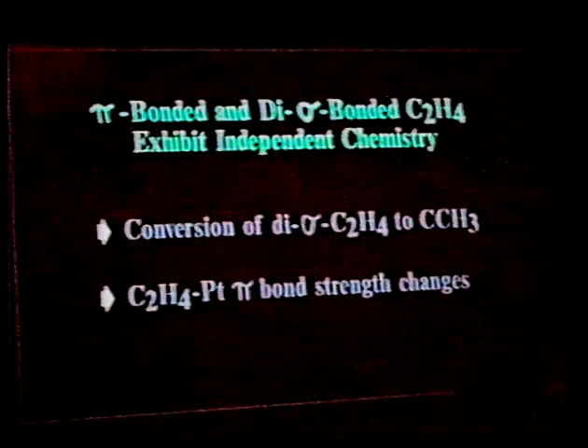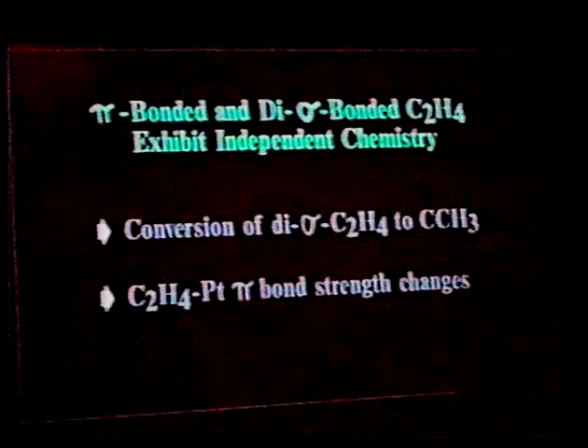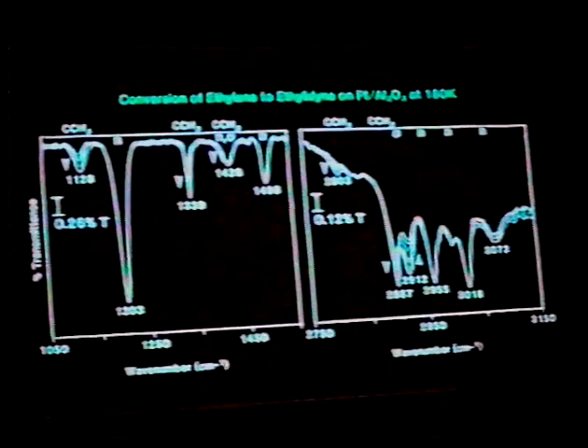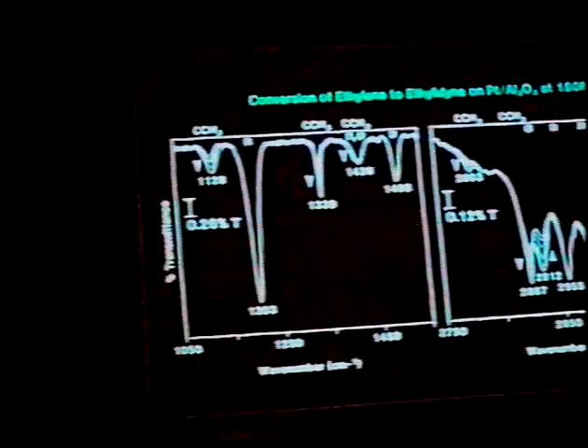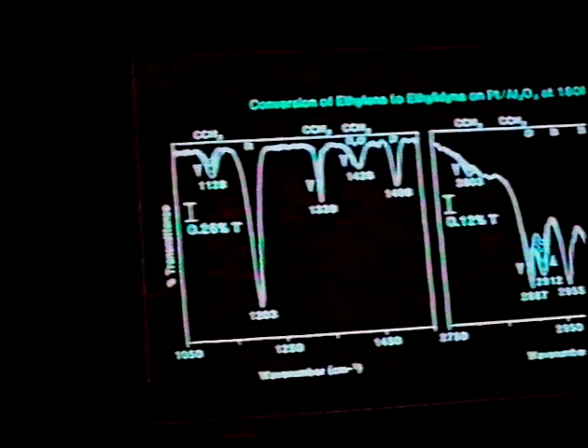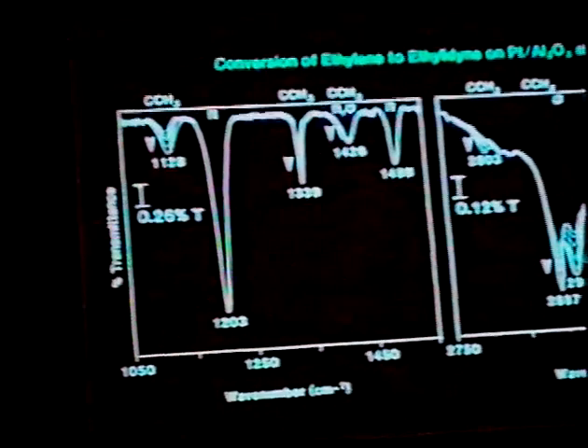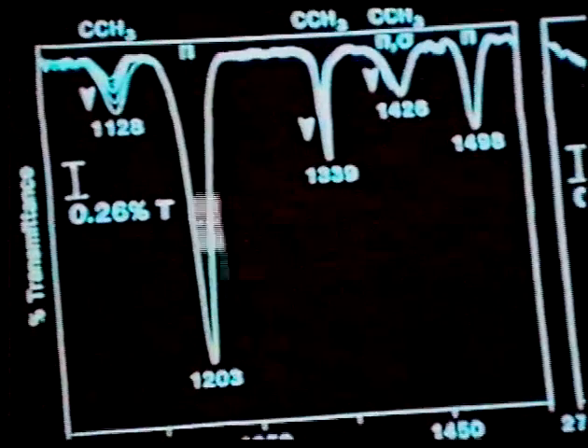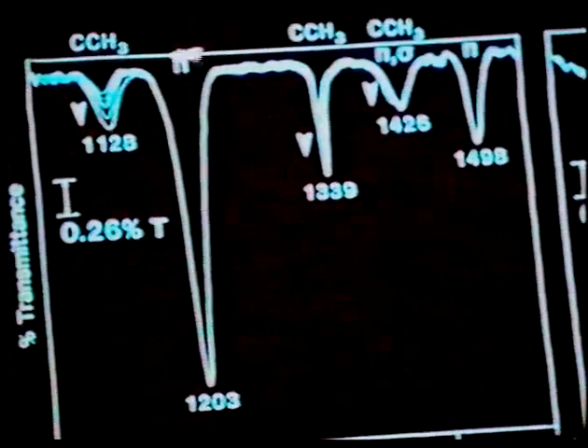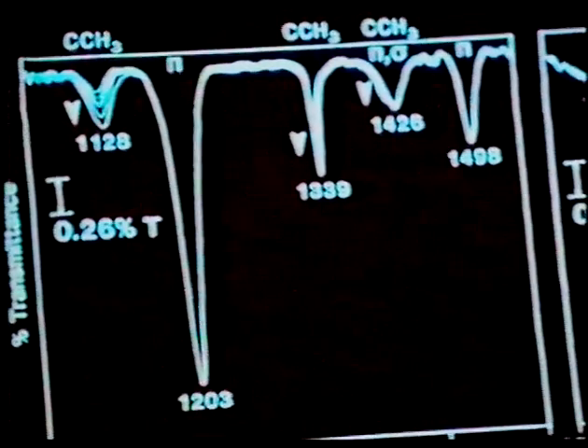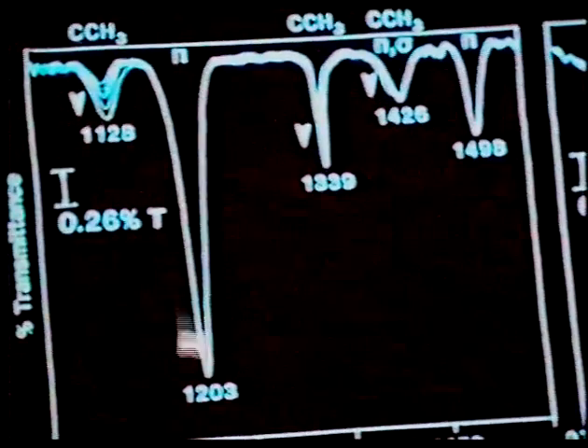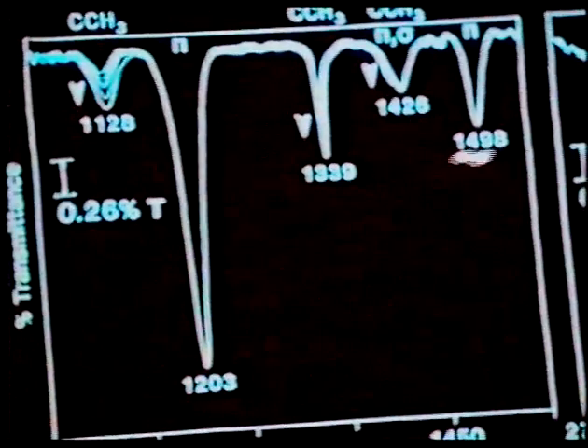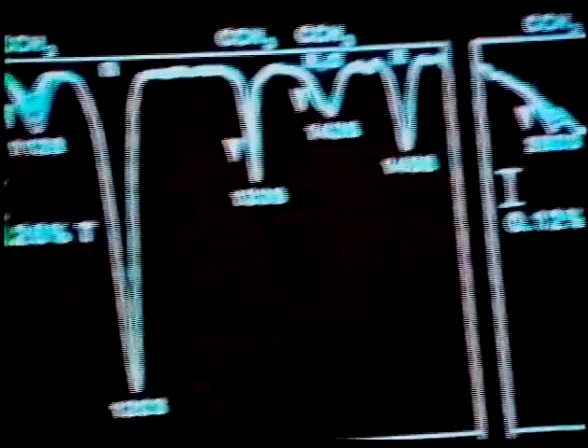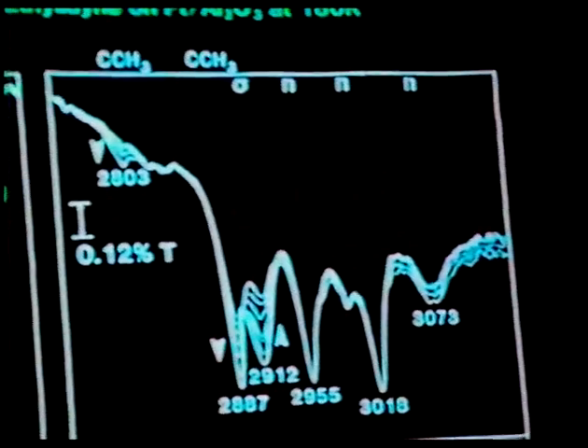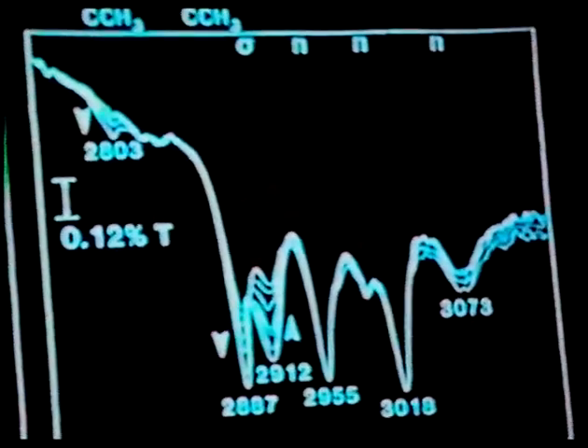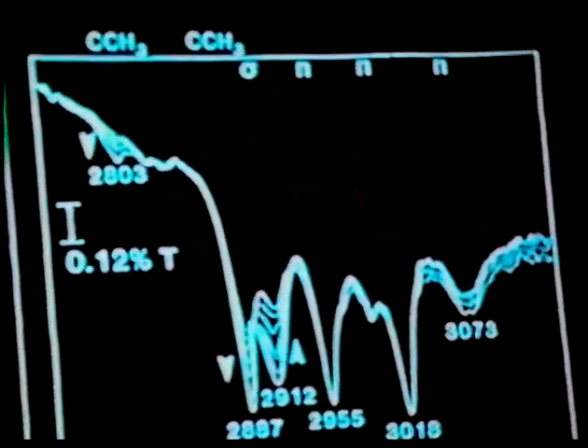It seems to be just a spectator as we change the chemistry of the pi-bonded. What I have here is a time-lapse collection of spectra at 180 Kelvin, and as you can see, the bands that are not changing are those that are related to the pi-bonded ethylene. The very strong 1203 band, there's really no change at all. Same with the 1498 band.